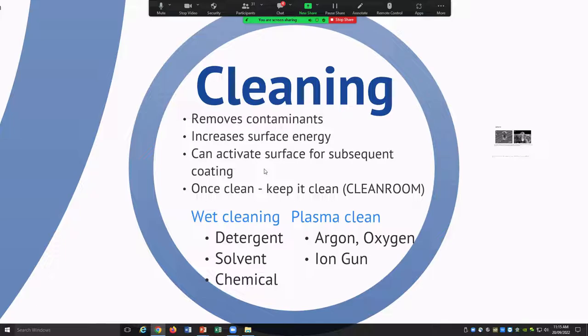Obviously, detergent, solvent or chemical cleaning. You might need to do a wet cleaning before you start, and then once you've got it into your chamber, normally you've got the ability to do some sort of plasma cleaning as well. So you could do a rough clean first using wet chemical techniques, and then move it into your vacuum chamber, and then do a plasma clean, surface activate, get rid of any adventitious carbon, and have a very receptive surface for your coating.